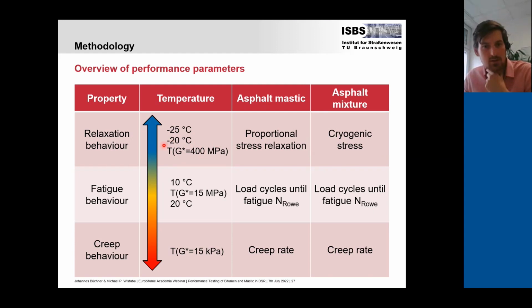Now, maybe I go into detail a little bit about why we included not only static temperatures here, but also shear modulus temperatures, since we wanted to analyze the applicability of those temperatures for performance tests. After this research, and also in the next research project, we slightly varied everything, but this was the first idea: that this low temperature shear modulus of 400 megapascal is quite in the range of -25 to -20 degrees, which is the critical temperature range for each of the binders used.